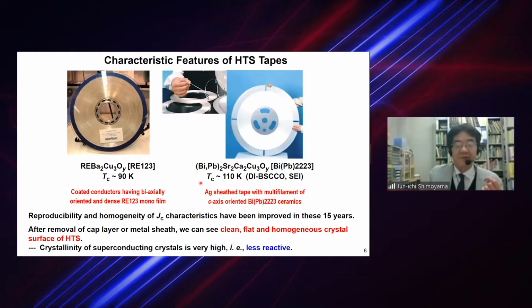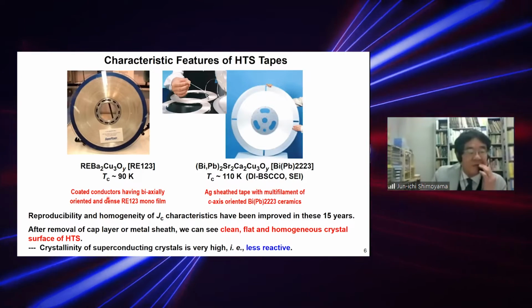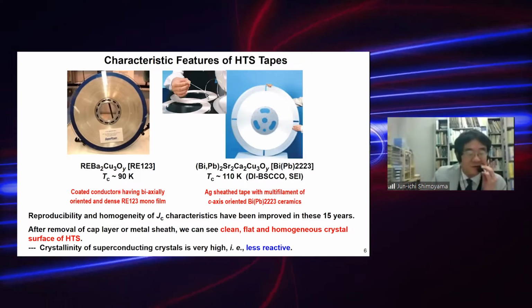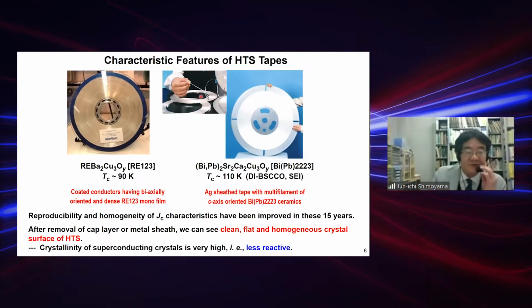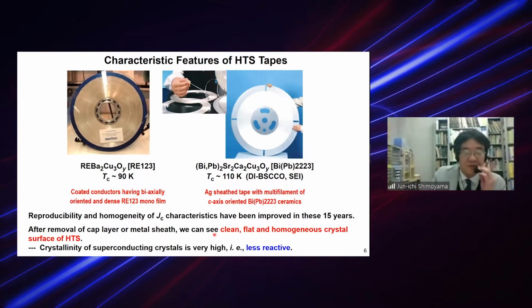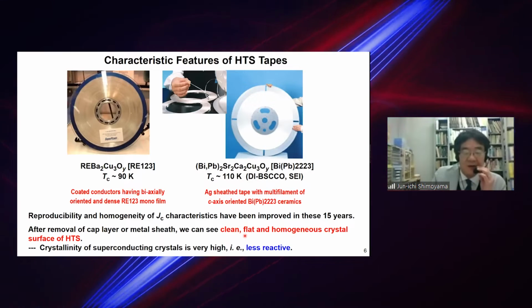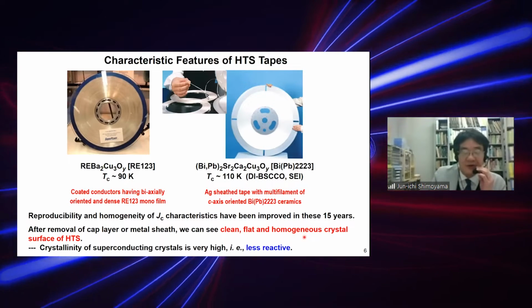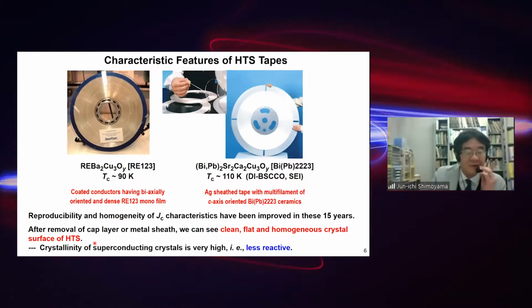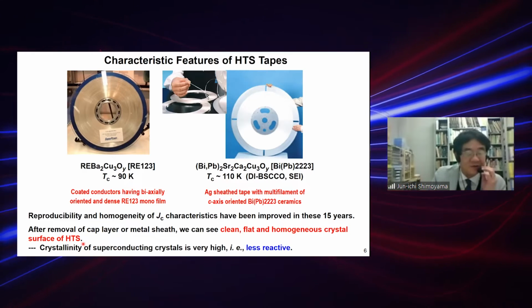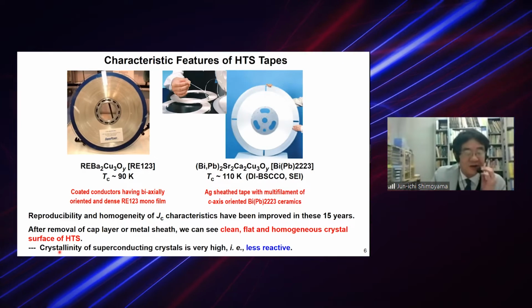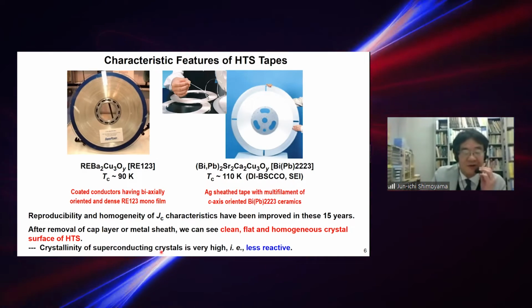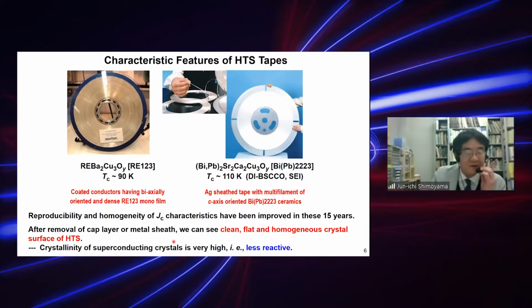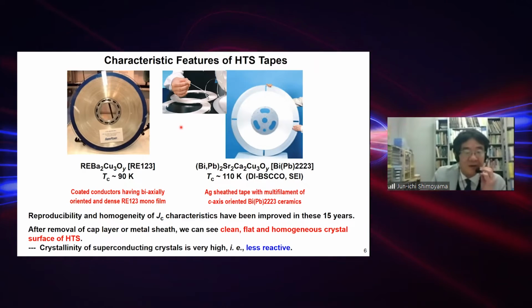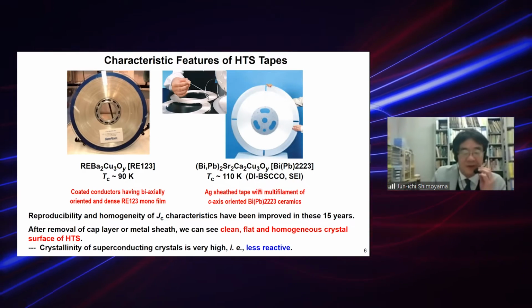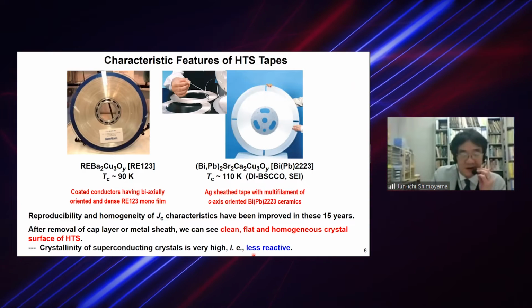But the important point is, when we remove the cap layer or metal sheath of those conductors, we can see a clean, flat, and homogeneous crystal surface of cuprate superconductors. That means the crystallinity of the superconducting crystal is very high at the top of the superconducting layer of those tapes. That means a less reactive layer.